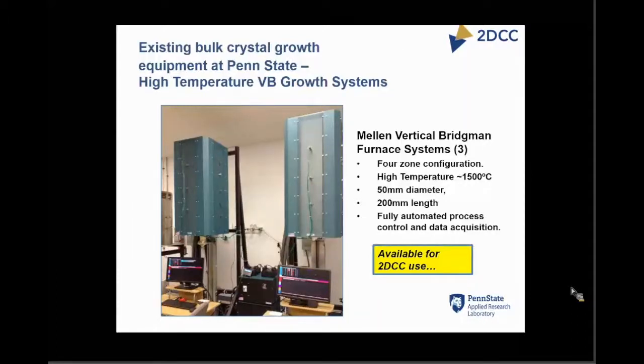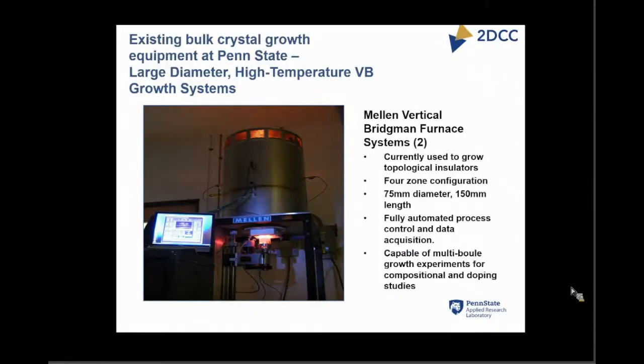And again, they're fully automated, data logging, process control. So they're very well suited. Primarily, we're using these for lead-based piezoelectric crystal growth at the moment. And again, the high temperature capability is what's of most interest. In addition, there are two other high temperature systems, which I'm calling large diameter high temperature vertical Bridgman systems.